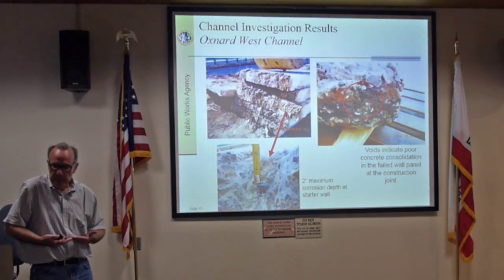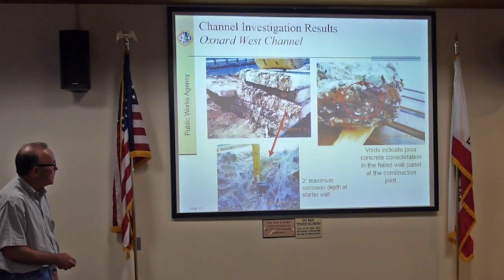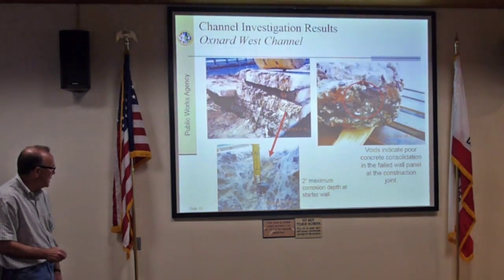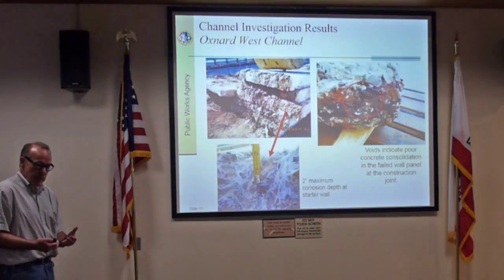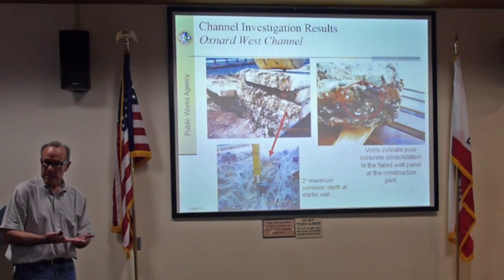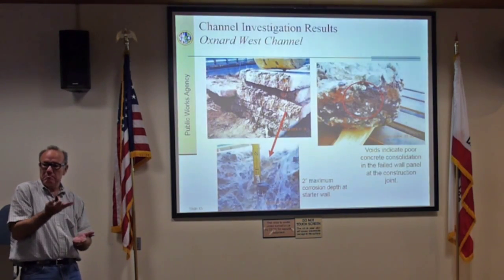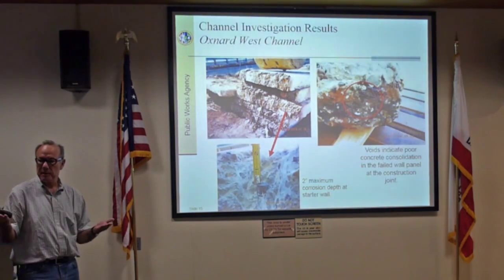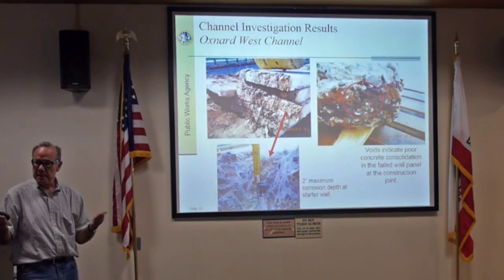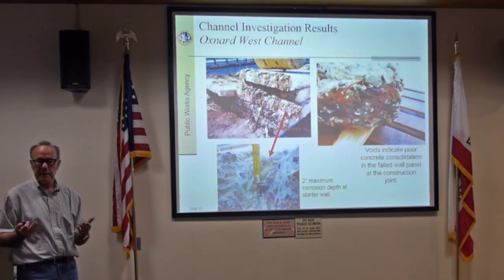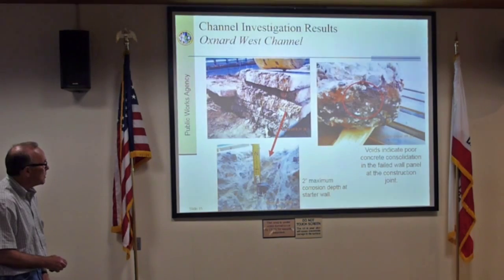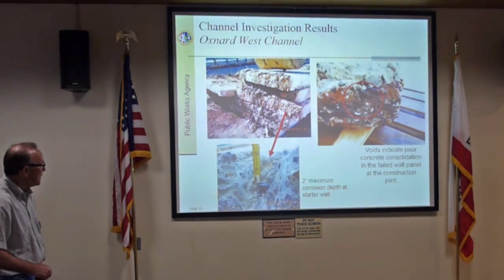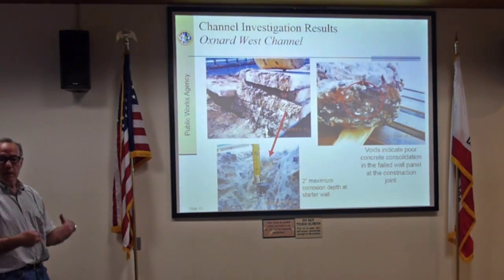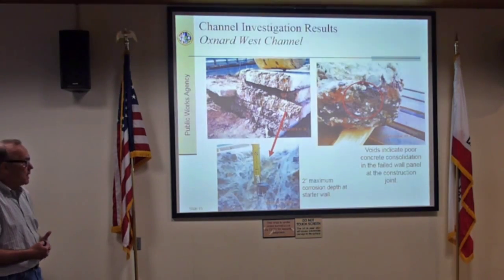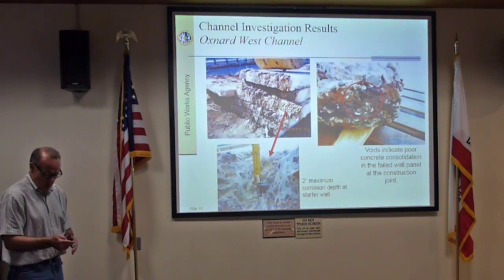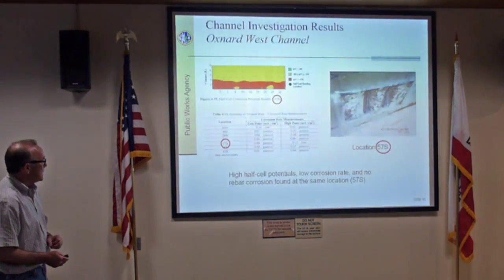It allowed a lot of penetration of water and oxygen over the years. You got a lot of corrosion products at this location. But it's very localized. It's right along that joint. You get 6 inches away from that, it's pretty much perfectly clean reinforcement, very well protected. So the challenge is really, can we detect this sort of thing without having to go in and look everywhere? And we'll talk a little bit about what we found from some of the results.